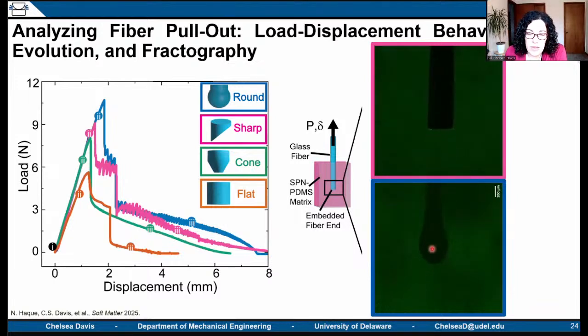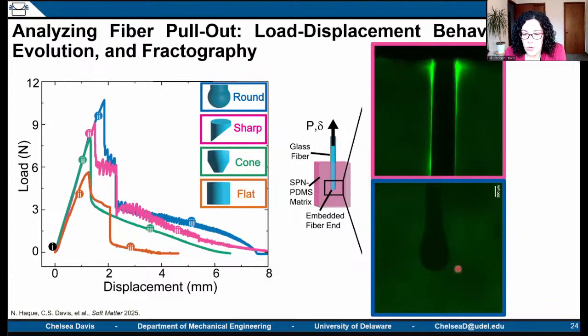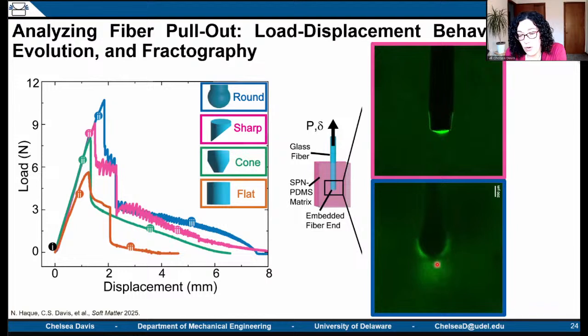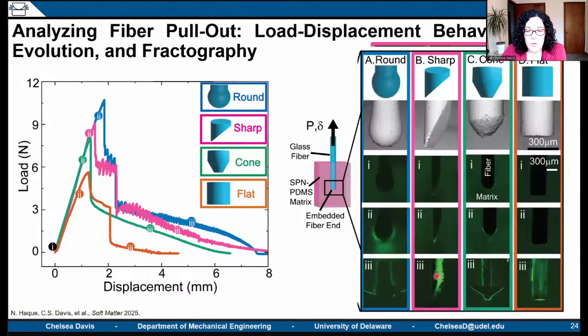Whereas if I play the round fiber geometry again for comparison, you can see that we get this very large region of activation prior to when we actually get failure in the bulk. I cut out that frame. So we can utilize mechanophores in order to see stress concentrations around all of these different fibers as they're being pulled out and then pulled through the matrix.